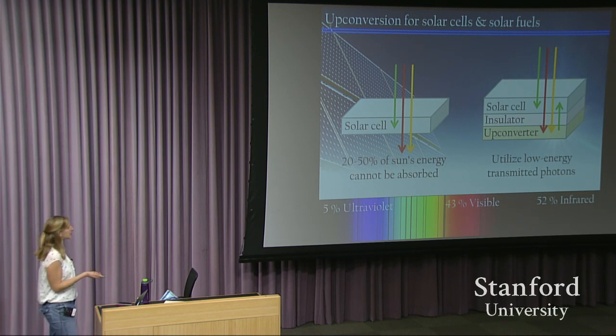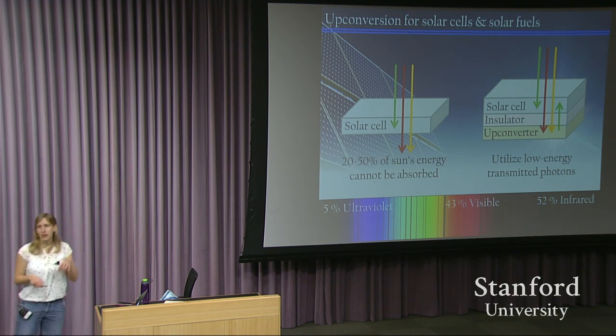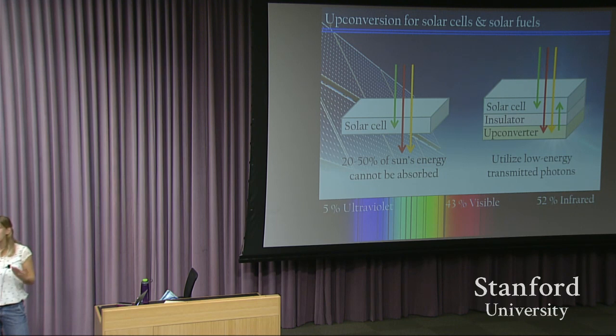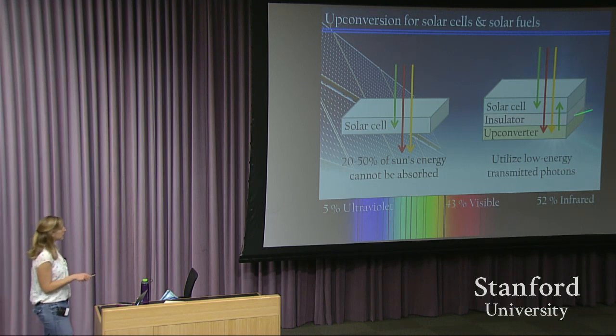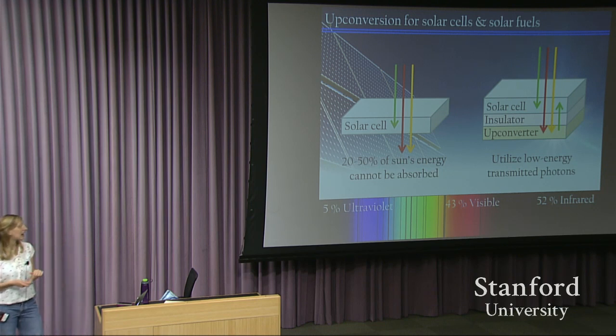So the idea of an upconverting solar cell or solar fuel is that you would place a material behind the solar cell that can take the lower energy photons and combine them together into a higher energy photon that then can be absorbed by the cell material or by the cell above it, contributing to photocurrent. And unlike a multi-junction cell, this scheme doesn't require, say, lattice matching, so you don't need to grow the upconverter behind the solar cell. You can just colloidally synthesize an upconverter and then spray cast or spin coat these nanoparticles on the back of a cell.